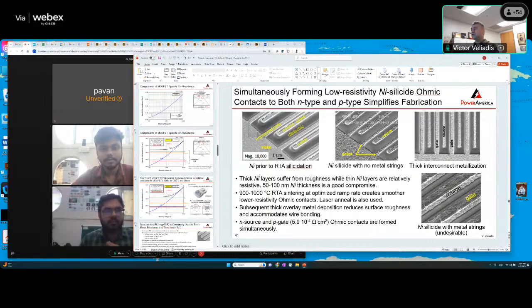So, if you're experimenting with this, I would start with this range right here and see what type of results I get. With respect to the rapid thermal annealing, I can send you a recipe that I tried and it worked well. I think it was 925 or 950 for about a minute and a half. So you have the whole wafer that basically goes into the chamber, and it's really a flash that creates that high temperature for a very small period of time, and that is sufficient to create the silicide.